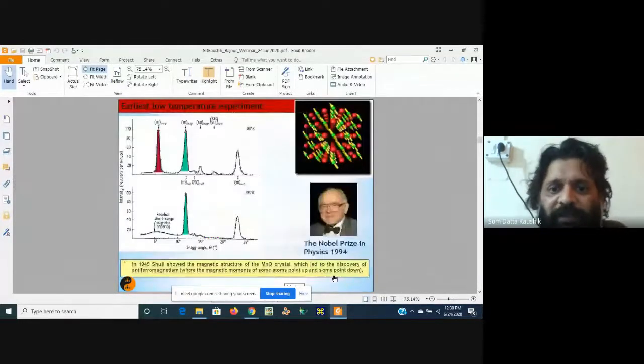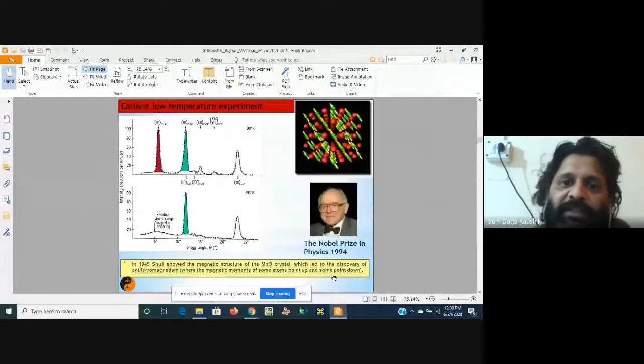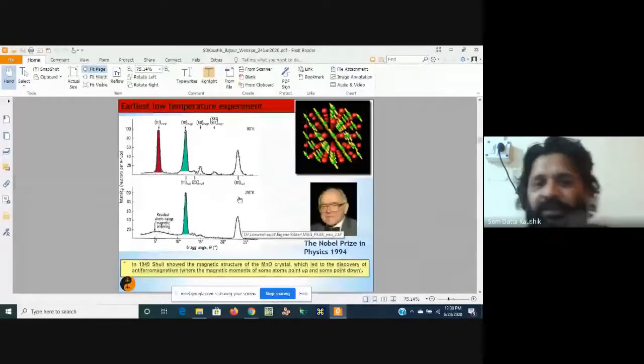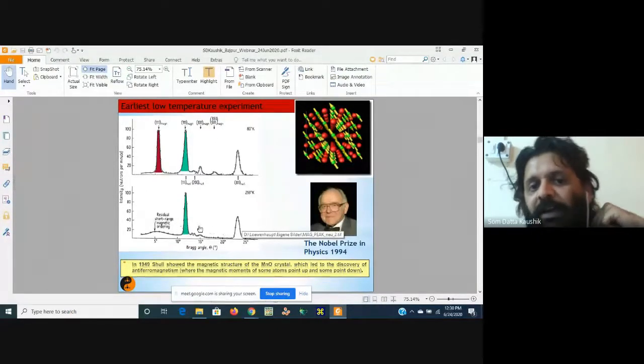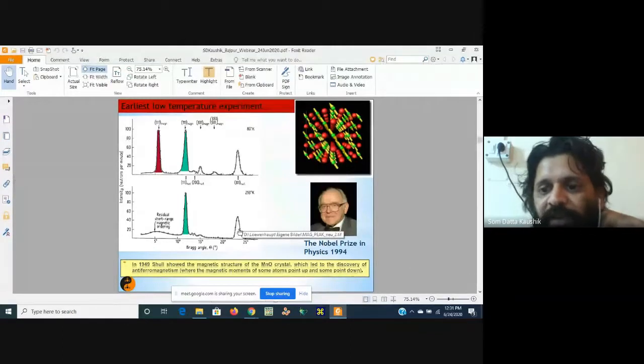So this is the very first example which was studied using neutron diffraction. This is the MnO neutron diffraction pattern, studied at 293 Kelvin. You can see these are the structural peaks. As you go down to, say, 80 Kelvin, you can see a few peaks coming up, and this particular peak is quite intense. This peak is basically a magnetic peak in your sample.